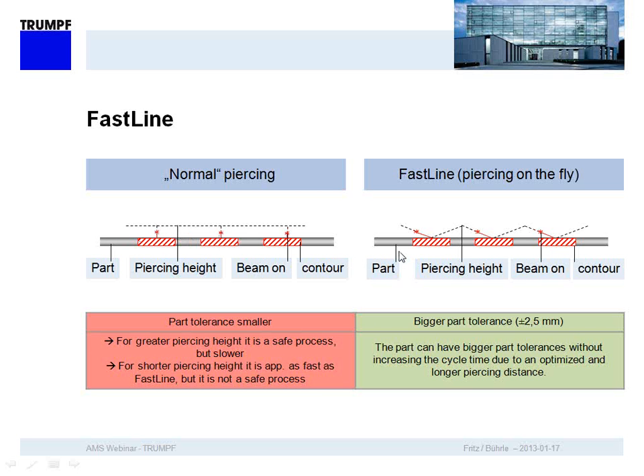With our piercing on the fly or fast line cell, while we approach the hole, we already ignite the beam and ignite also the distance control. So we have already the very high energy density on the part when we come to the piercing position. That means we can start to cut this hole much faster. What we save here is roughly 200 to 250 milliseconds for each time that we do this piercing. So now if you count a typical part, maybe 20 holes, well, you can do the math.